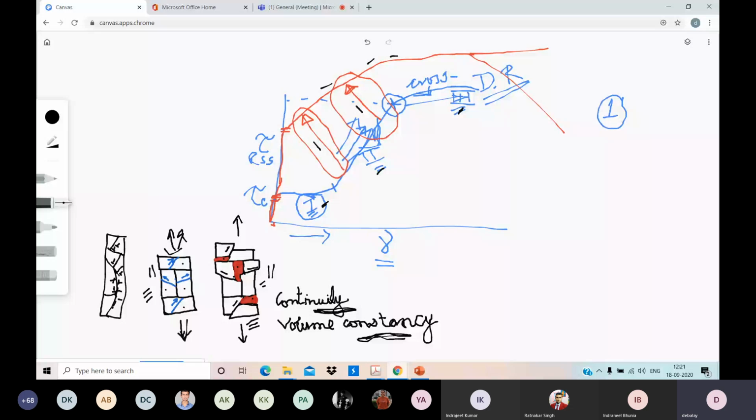So in single crystal, some amount of deformation will come, which will cause plastic deformation, because one dislocation through-and-through movement leads to one atomic spacing slip. So 1000 dislocation movements are necessary for 1000 atomic spacing slip in a single crystal.